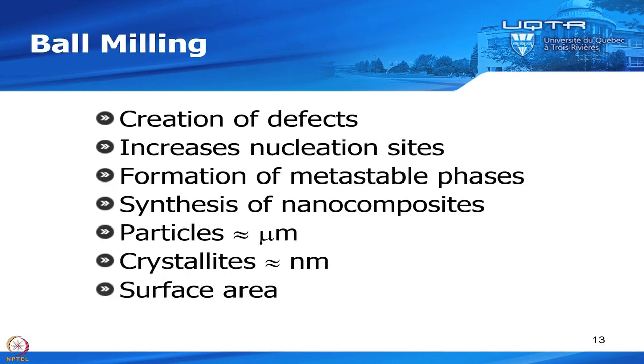So today we will look mainly at ball milling to prepare metal hydride. This is the technique that is used by most of the researchers in the field of metal hydride. Almost all of them are using ball milling to get a nanocrystalline structure. And as we saw, by ball milling, you could have defects, so that will increase the nucleation sites. You could have formation of a metastable phase. This is a common feature of ball milling, not only in metal hydride, but also in other types of material. Usually you could get a metastable phase, a high pressure, high temperature phase, just by ball milling at room temperature.